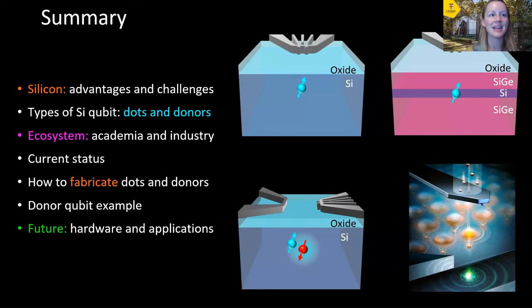So for the first case, we've got the scanning tunneling microscope, which uses the very small tip of this microscope to rip off the hydrogen atoms to be able to pattern this hydrogen lithography on the silicon surface. And then you incorporate the phosphine gas molecules and you get the phosphorus atoms sticking into the positions where the hydrogen was removed. And then you can incorporate these phosphorus atoms into the silicon by growing over with a silicon layer. And this has a really nice benefit of being able to very precisely, to within the order of the atomic lattice site position, the donor qubits in silicon, which gives you really strong tunability of how the coupling between the two qubits goes. However, on the downside, when you're removing the hydrogen, it's quite hard to remove a specific number of hydrogens. And so you might end up incorporating not just one, but a cluster of phosphorus donors. And so it's harder to control the number of donor qubits, but it's easier to control the position of the donors when they get there.